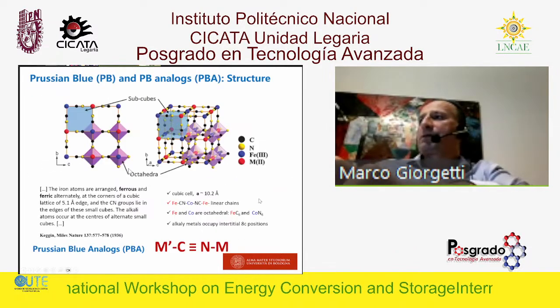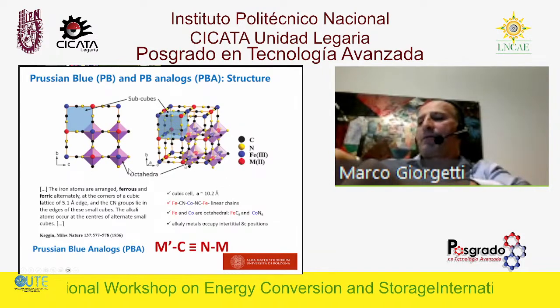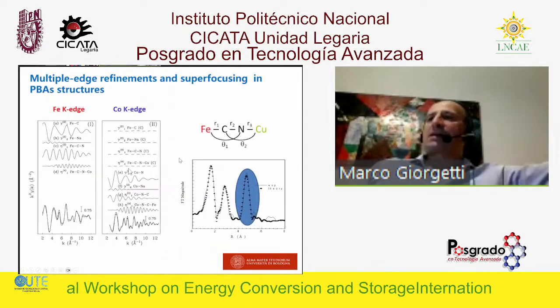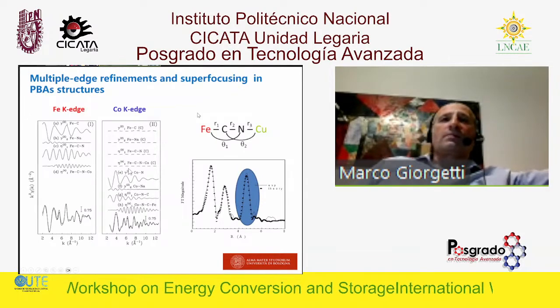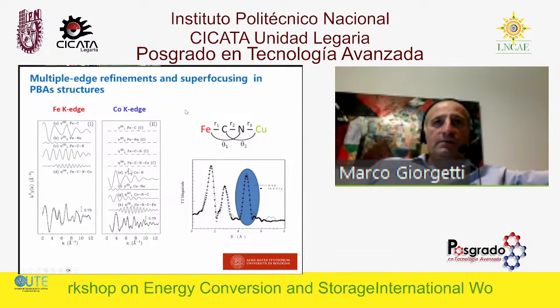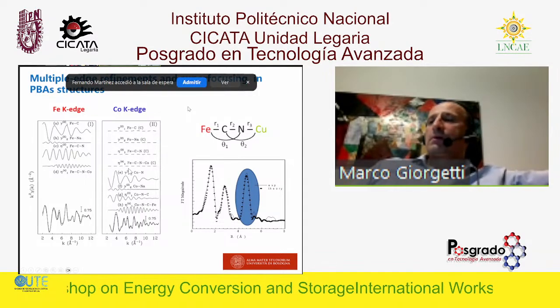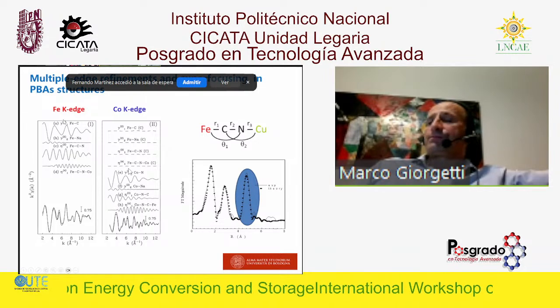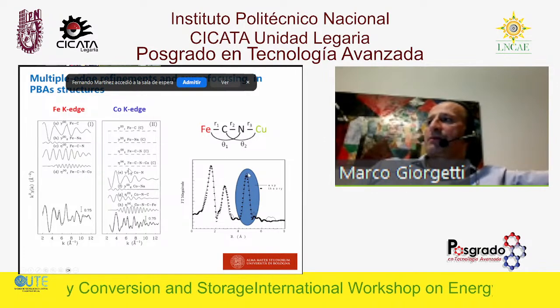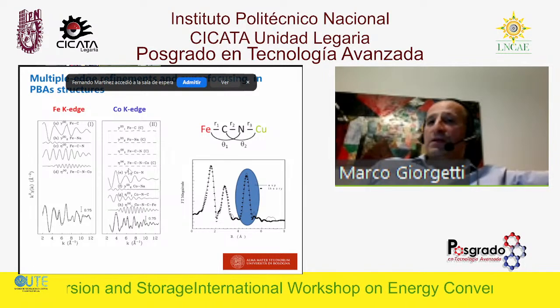And we know that if the cube is about 10 angstrom, the distance is, of course, half, about 5 angstrom. So in that case, it can really extend the local coordination probe, the typical EXAFS. So in metal cyanoferrates it can be extended that far, and then in the Fourier transformation of this EXAFS from, for instance, the iron side, you can see from here we have three peaks. One is the carbon, the other is nitrogen, the other is the copper. So this is expected, the third peak is very intense, very large. This is due to the four-body contribution, due to the linear chain of the metal cyanoferrates.